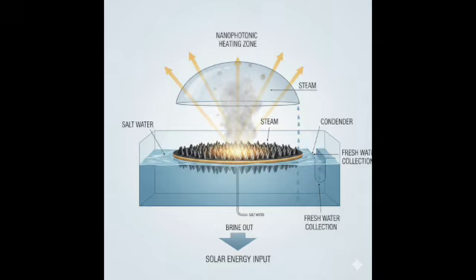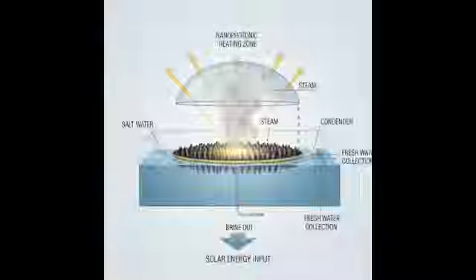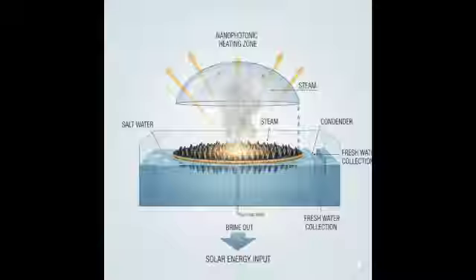Because the heat is generated right at the feed membrane interface, that interface temperature, T_fm, now becomes higher than the bulk feed temperature, T_fb. So you're reversing the problematic temperature gradient, T_fm less than T_fb, caused by evaporative cooling in CMD. Now you have T_fm greater than T_fb. Exactly. You're generating the heat precisely where evaporation occurs, overcoming the latent heat loss locally and establishing a highly efficient temperature gradient across the membrane pores.